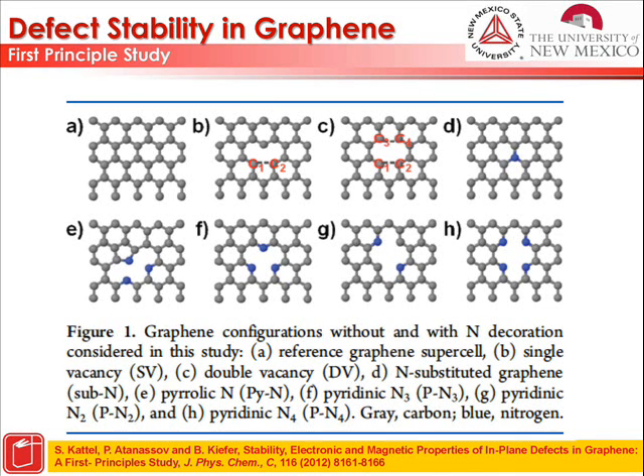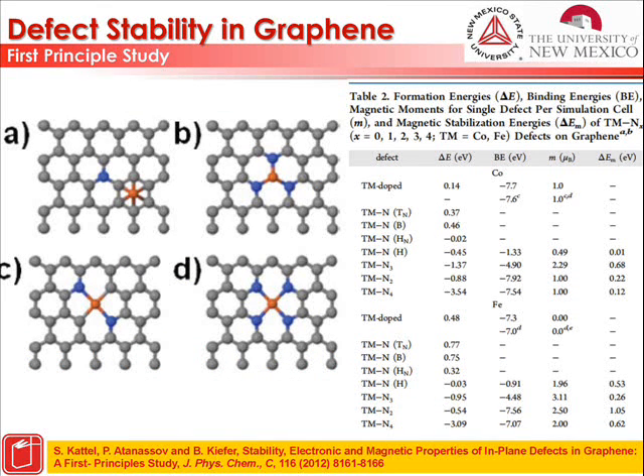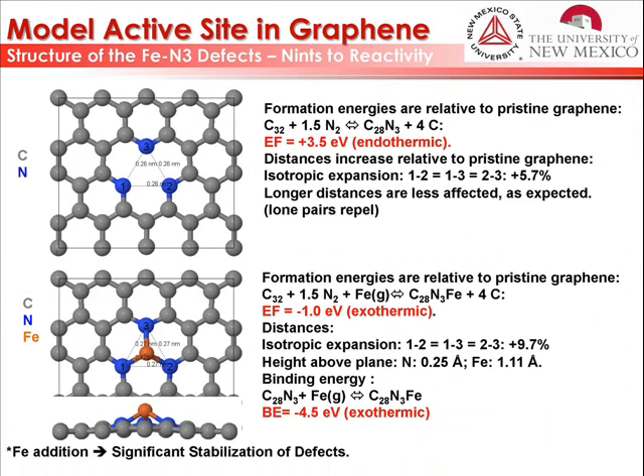and it's very easy to make energetically. And that site is 3N with iron. That is not a published site yet in terms of performance, but it is a published site in terms of prediction. And now you will see, Plamen, of course, that site is very similar energetically to the N4 site, but it is easier to make if you look at that from a making of defects into graphene.